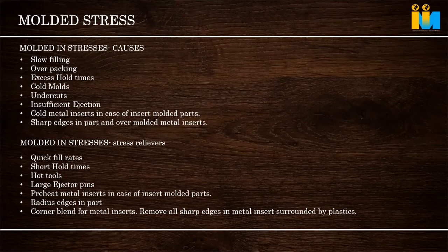So that has happened. Near the molding machine, some arrangement has to be made to heat that. And while heating the insert, heat it an extra 10 or 20 degrees before putting it in, so that when the injection happens, some cooling occurs during mold closing, and it comes to the right temperature. That gives a good result. If you have cracking in the metal insert boss, wherever the thread is, this is going to solve your problem.